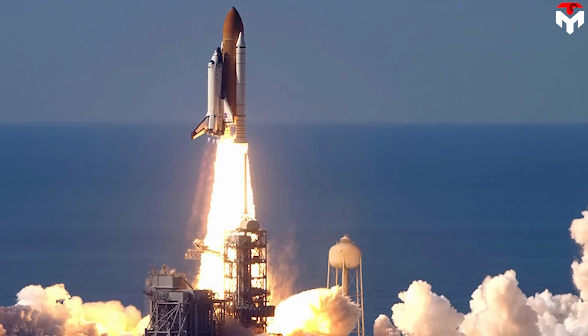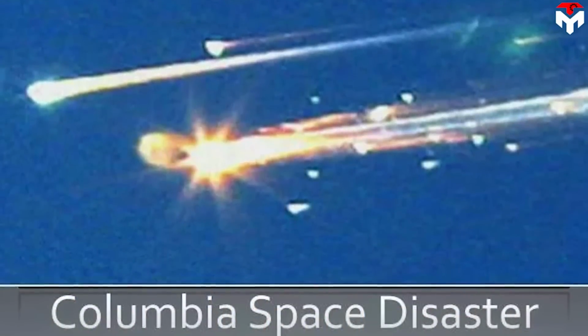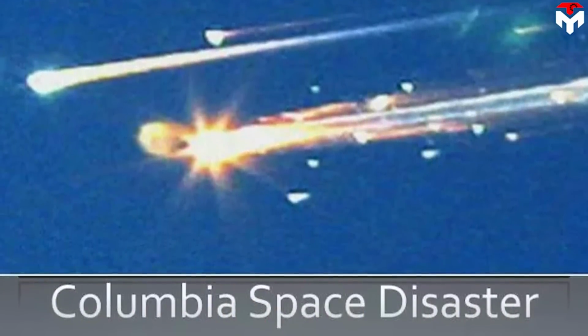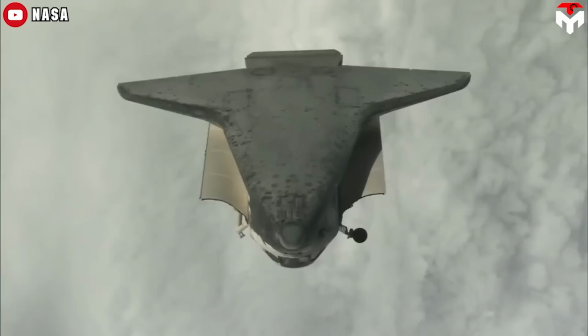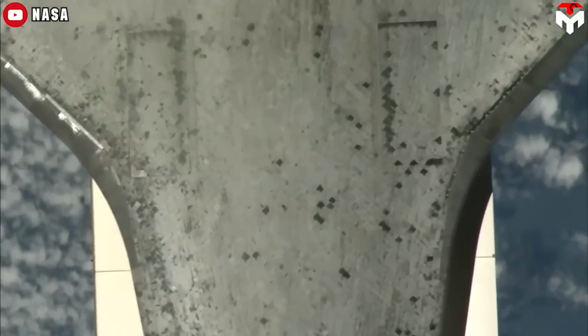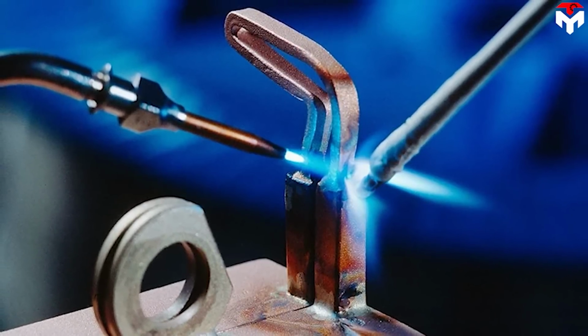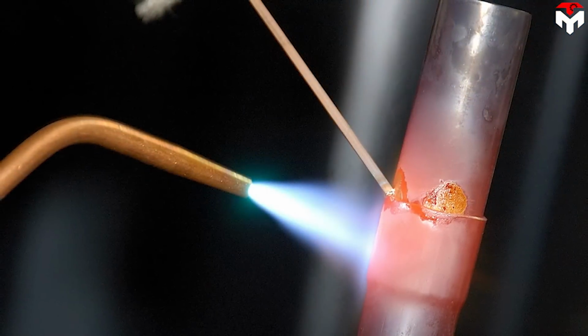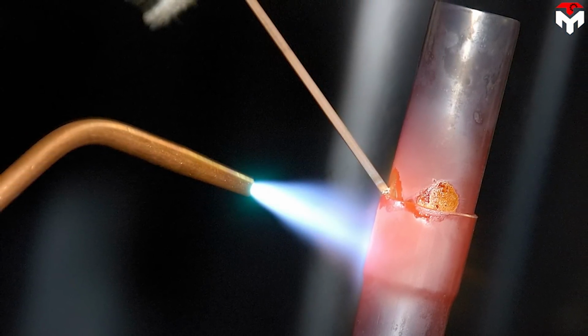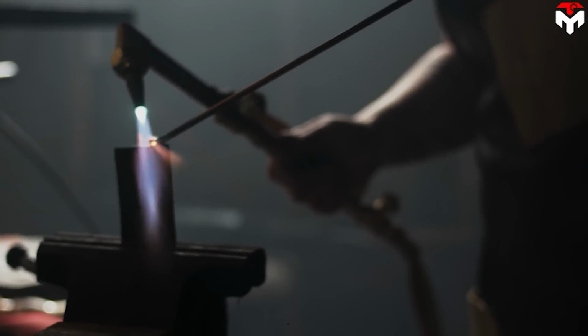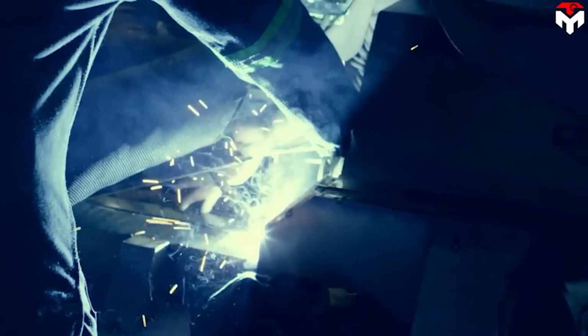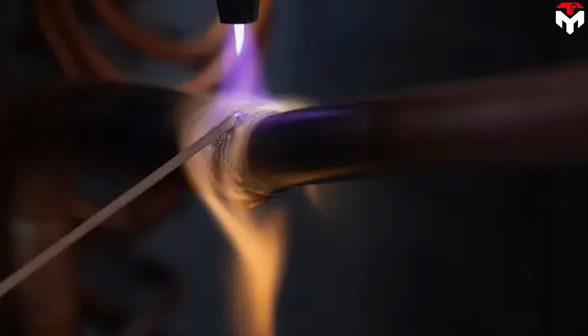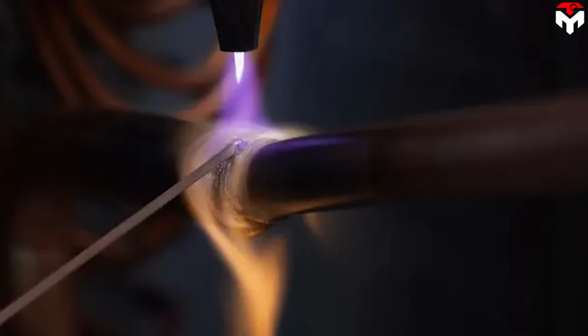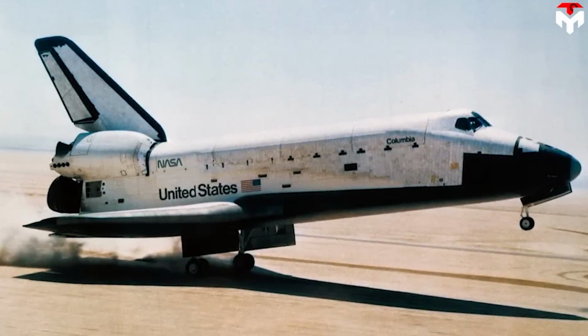This would cause the degradation of the bonds and the loss of more tiles, exposing the shuttle body to extremely high temperatures upon re-entry into the Earth's atmosphere. According to Chung, there are other, more heat-resistant ways to connect tiles to the shuttle body. Brazing, which is like soldering except that it involves higher temperatures, creates joints able to withstand temperatures as high as 1,000 degrees Fahrenheit, depending on the brazing material used. In contrast, adhesive joints can only withstand much lower temperatures, around 250 degrees Fahrenheit. Brazing, however, is a more expensive and involved process than adhesion. This could be a reason that it wasn't used for the Columbia, Chung says.